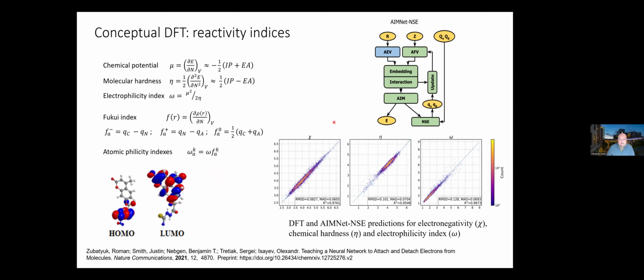What was also interesting, and this is another direction, called differentiable physics, is that in chemistry there is an extension for density functional theory called conceptual DFT, which connects partial derivatives of the energy with respect to the total number of electrons. These are total quantities, but there are also condensed properties per atom. Since the neural network is fully differentiable, we can bypass QM calculations and extract those first and second derivatives directly from the neural network, and therefore compute all those quantities that can be applied to downstream tasks of predicting reactivity and other property calculations.